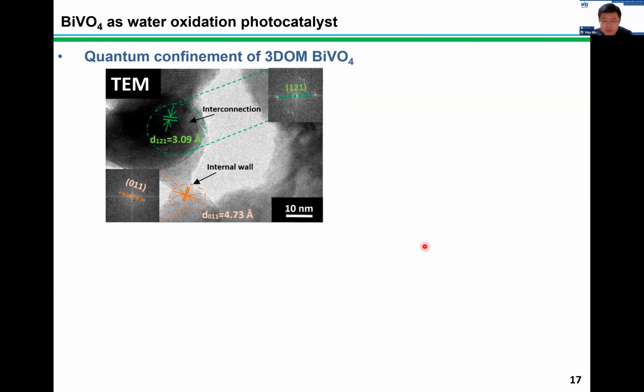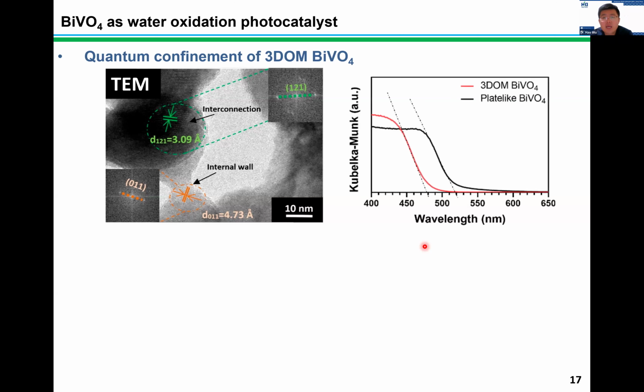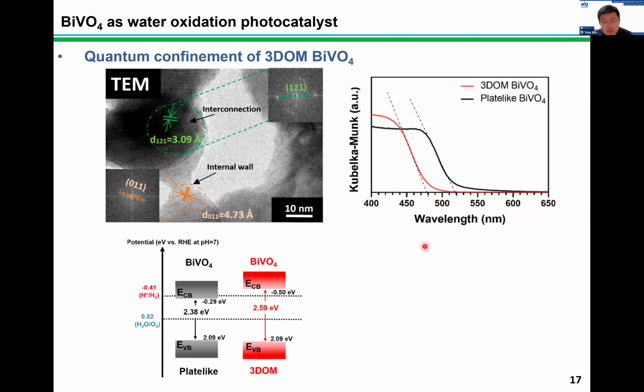the photo-induced carriers. So to prove such an effect, we first did the UV measurements of our samples, and we found that compared to its bulk counterpart, the three-dimensional bismuth vanadate shows a blue shift of light absorption, indicating its enlarged band gap. And upon combining with the UPS results, our results show that compared to the bulk counterpart, the quantum confinement effect uplifted the conduction band position of bismuth vanadate, enabling it to be thermodynamically powerful enough to reduce protons to generate hydrogen.